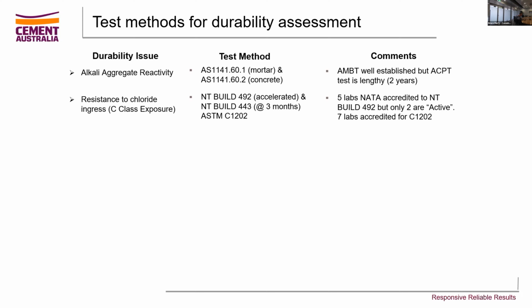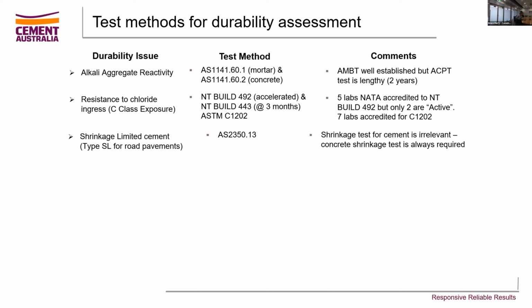The 443 test takes a bit longer. That takes 3 months, or you actually test the concrete at 3 months. And this is more commonly run by laboratories across the country, but it's quite an expensive test. It's like $2,500 per concrete mix. And then finally, one here that's very commonly specified here in Queensland is similar to the 492. It's the ASTM C1202. And only 7 laboratories are accredited to do this test. So we're not really sure how many of those are active.